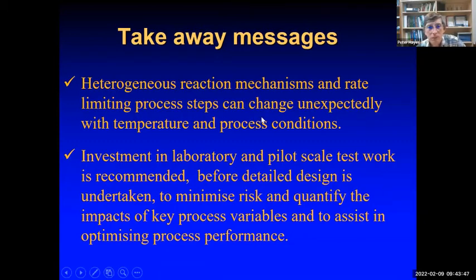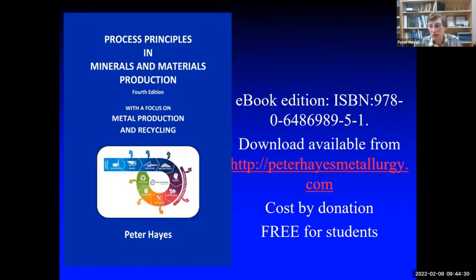So what are we going to do about it? Well, my advice is to make sure you do enough experiments. I'm an experimentalist, basically. And I suggest that before you design in detail your large plant, you make sure you do enough laboratory and pilot scale test work to ensure that you don't get these unexpected and unwanted changes in reaction mechanism as you change the process conditions. That is either the thermodynamic driving force or the temperature. We need to know what's going to happen before we make this large investment in the processing plant.